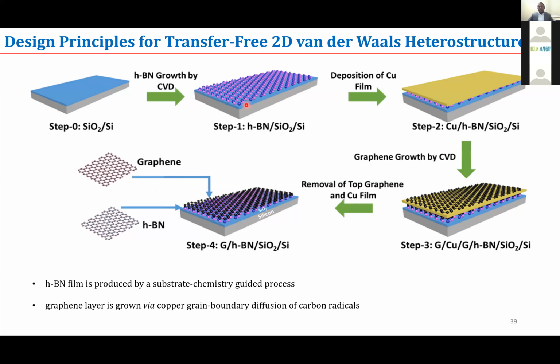And then we use a layer of polycrystalline copper and introduce hydrocarbon-based, gaseous sources, to produce graphene at the interface of boron nitride and copper. Then we can remove the copper, and then we will be able to get the graphene on boron nitride heterostructure.